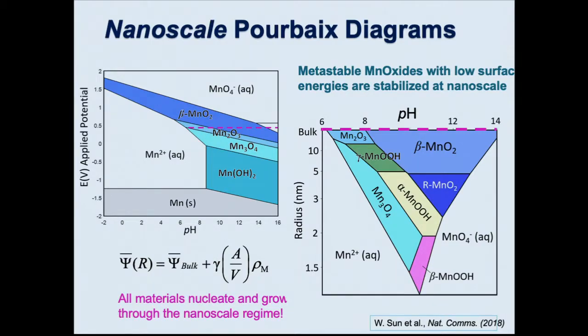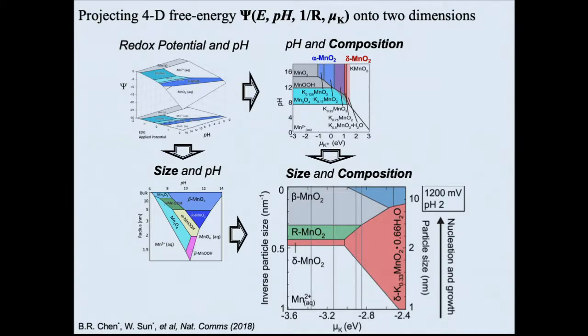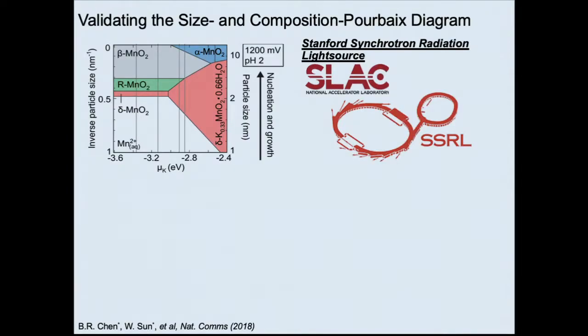But if you go to smaller size, these other phases start to appear, right? The oxyhydroxides are starting to appear on the diagram. Actually, the spinel appears even though we're not in the bulk phase stability region of the spinel. And so what you're seeing is that these oxyhydroxides could be stabilized just as nucleation preference by size. So you can put all this together in some formalism: size, pH, et cetera.